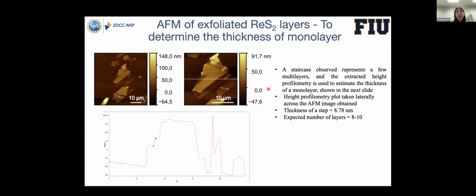And after we exfoliate the material and put it onto the silicon substrate, we wanted to know what kind of thickness we get for those layers. So in order to do that, we learned how to do AFM imaging, and this is the AFM image of one of the layers. We tried to find an area where we have a staircase kind of feature, so that when we do the height profilometry, the step size would give us an idea of how thick the layer could be. In our case here, it was nearly 8 nanometers, and we are expecting that the number of layers here would be nearly 8 to 10 layers.